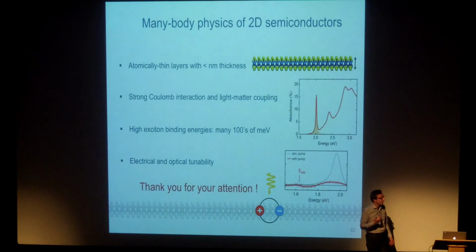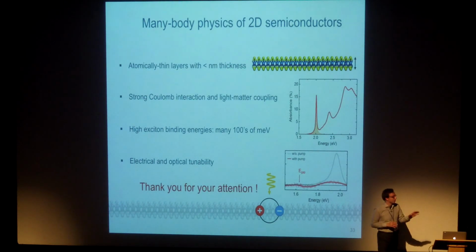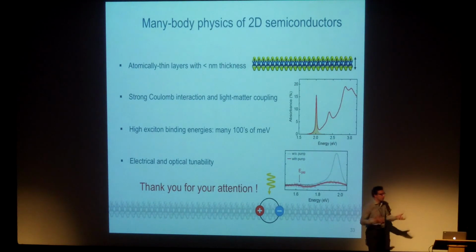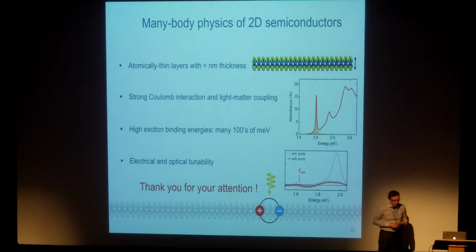It's rather similar to graphene, and that is one of the reasons actually, and I didn't talk much about it, but the recovery we observed at these time scales can, and to a large degree will, be related to cooling. It's still rather fast in comparison to, let's say, a bulk, buried quantum well, which has to transfer a lot of heat. The contacts themselves, of course, are not very well defined, especially in the systems where we just exfoliate. So we have a rough surface, some atoms trapped in between. But basically, the proximity, in this case, is the thing which helps.